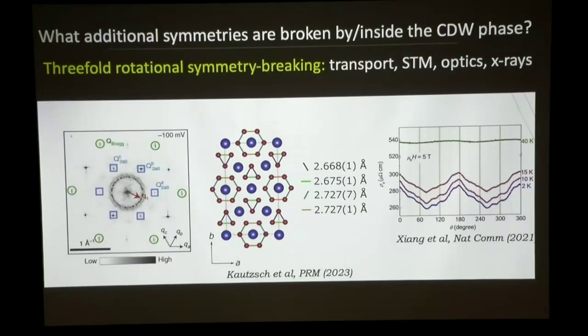The interesting thing is that the charge density wave transition is associated with a pretty large lattice distortion. This means that there is very strong coupling between electrons and phonons in the system. So one question you can ask is, what additional symmetries does the CDW break? If you look at the Fourier transform in the previous slide, or actually I have it here, you can see there are these 6 CDW peaks. And in theory, the intensities of all these 6 peaks should be identical, so they shouldn't break any additional symmetry. But it turns out that that's not true.